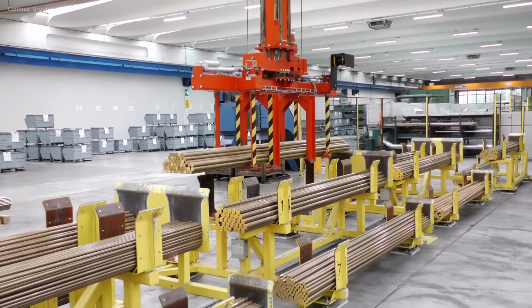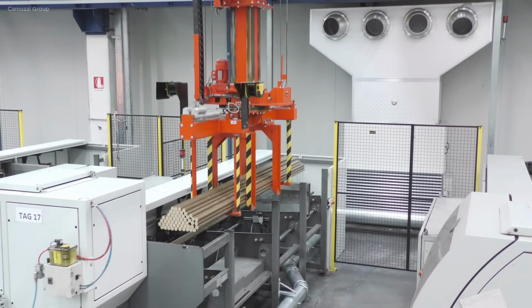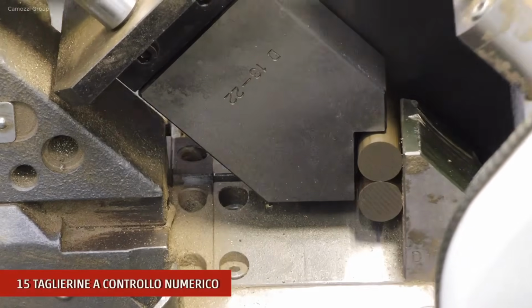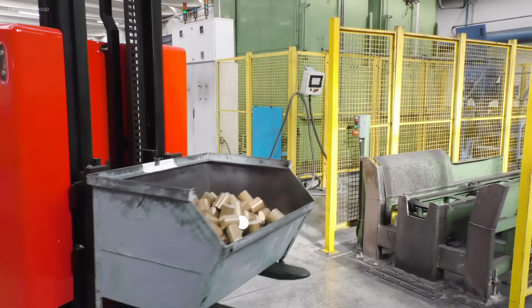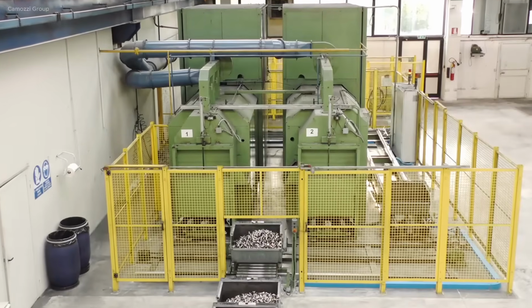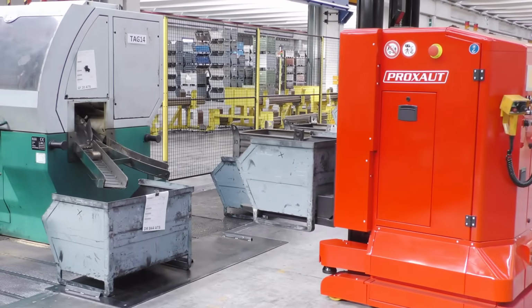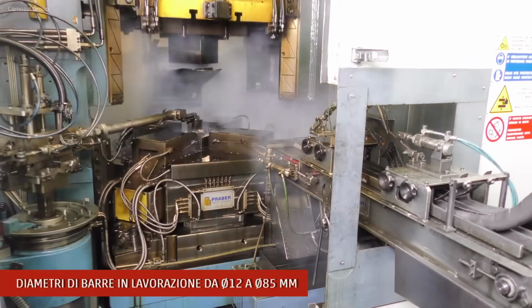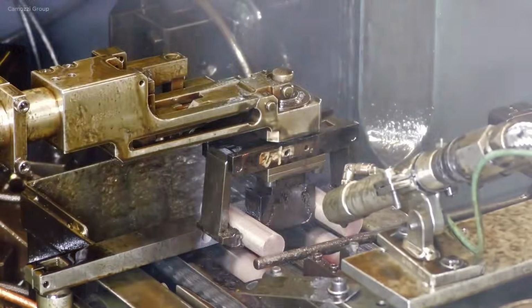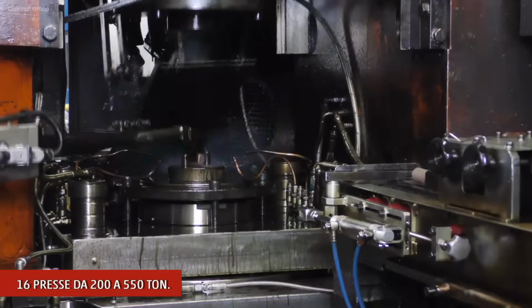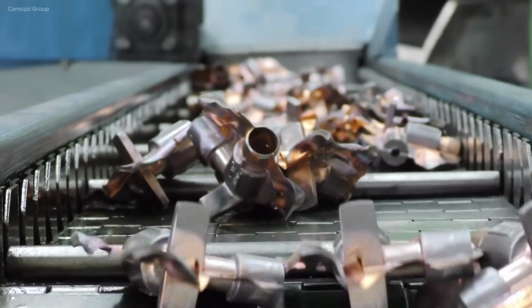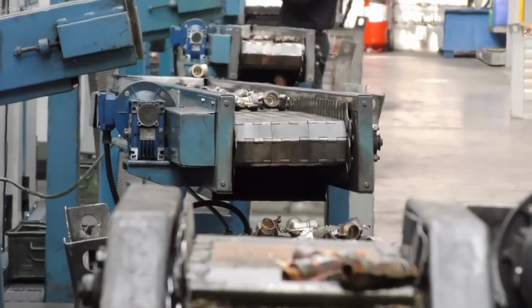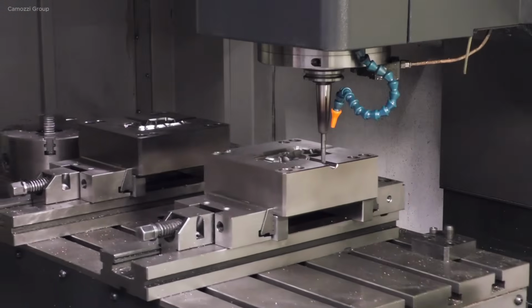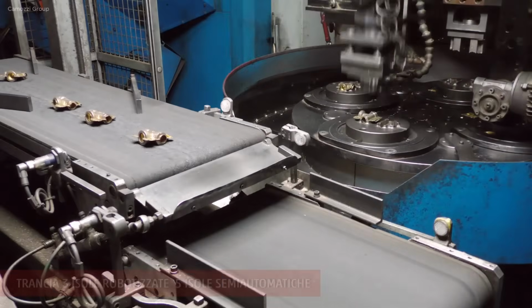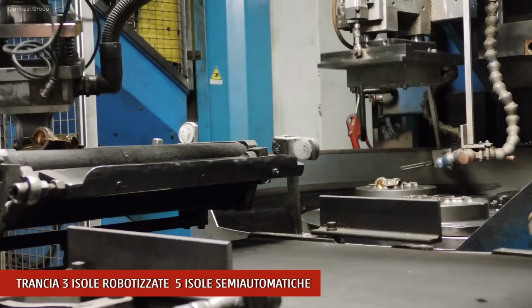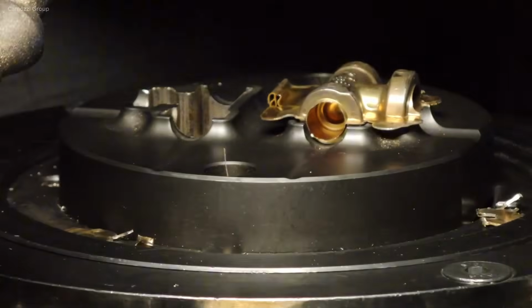The brass forging process begins with mold design and bar cutting using 15 CNC saws for diameters from 12 to 85 millimeters. Cut pieces undergo graphite coating before hot forging with 16 presses ranging from 200 to 550 tons. Forged parts are trimmed using robotic and semi-automatic cells. Sandblasting follows for surface cleaning. Finally, parts receive custom mechanical machining and finishing. Camozzi forges 13,000 tons of brass yearly, from 5 grams to 6 kilograms.